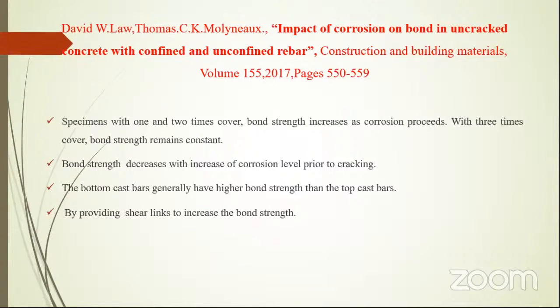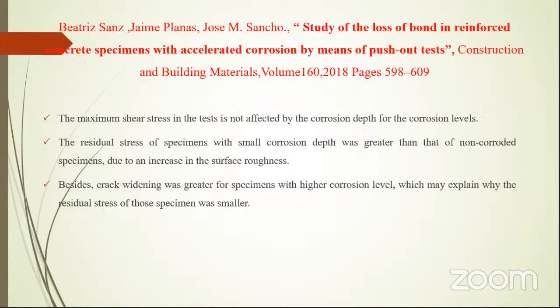The next literature is about the impact of corrosion on bond in uncracked concrete with confined and unconfined rebar. In this literature, the paper deals with specimens with 1 or 2 times cover, where bond strength increases as corrosion proceeds, while with 3 times cover bond strength remains constant. Bond strength decreases with the increase of corrosion level prior to cracking. The bottom cast bars generally have higher bond strength than the top cast bars, and providing shear links increases the bond strength. The next literature is about a study of the loss of bond in reinforced concrete specimens with accelerated corrosion by means of push-out tests. This paper deals with the following point. The maximum shear stress in the test is not affected by corrosion depth for the corrosion levels.